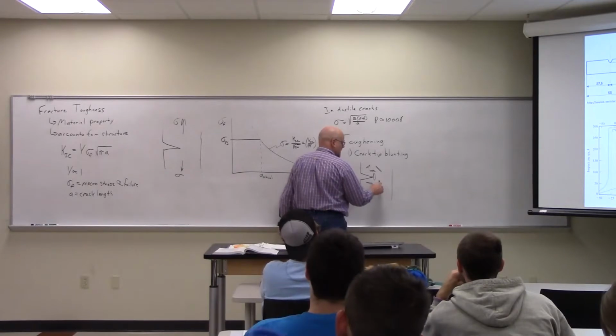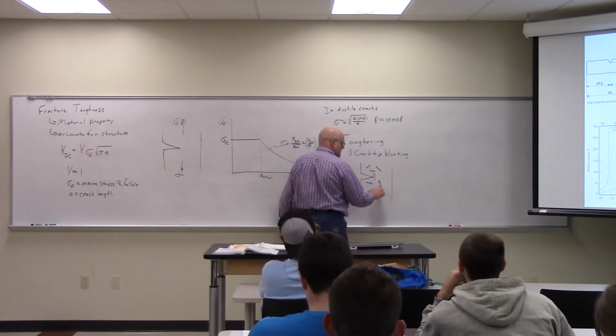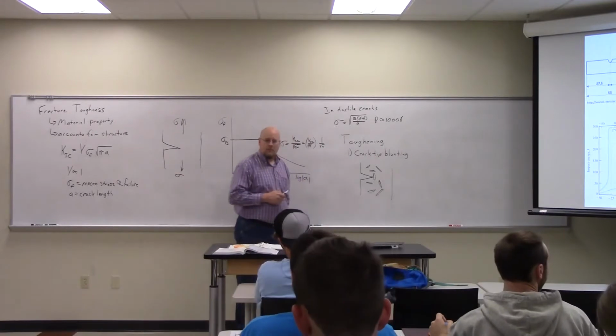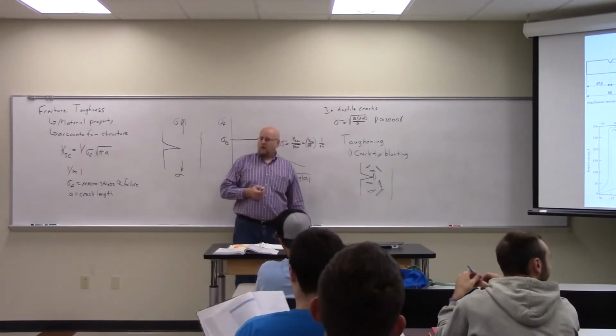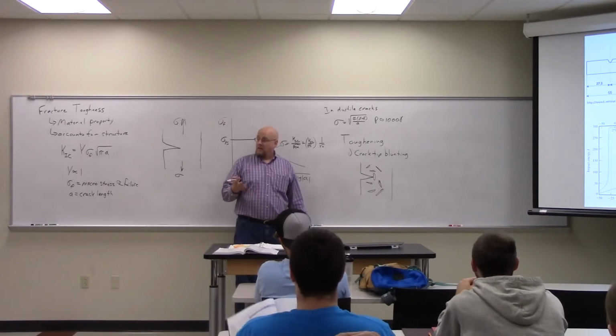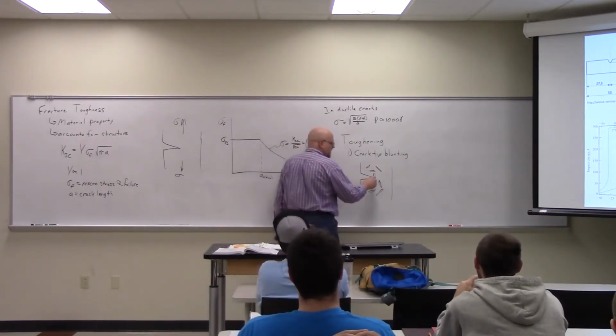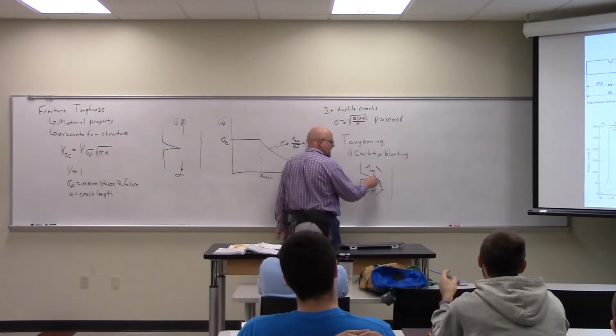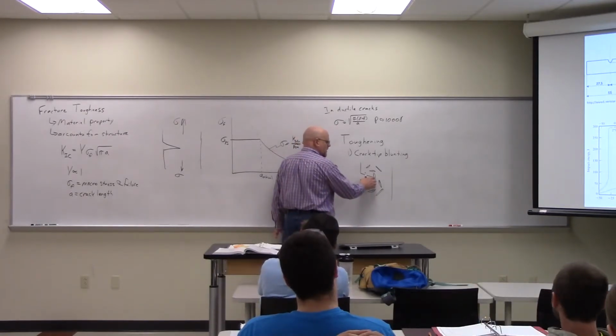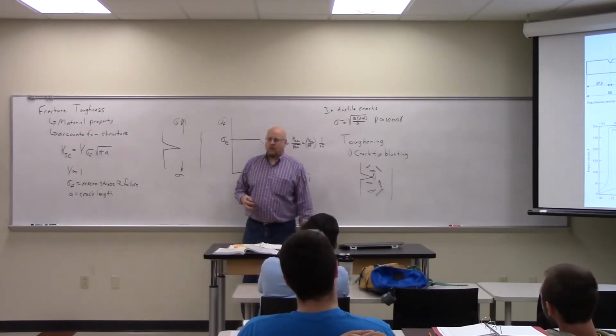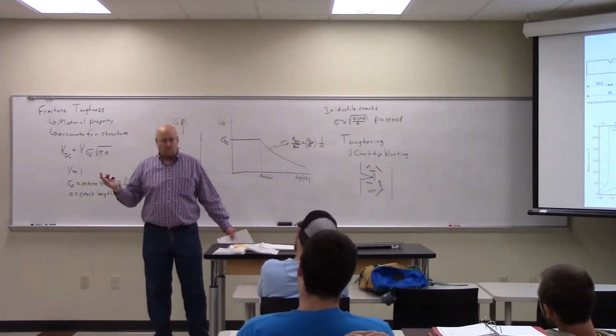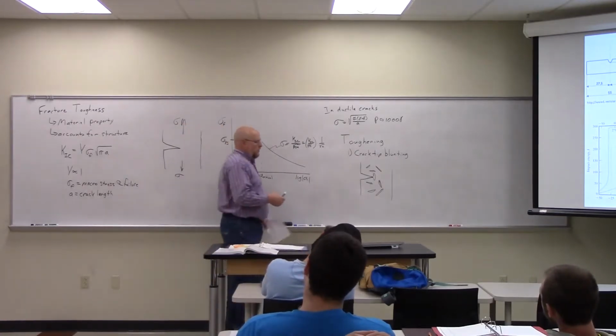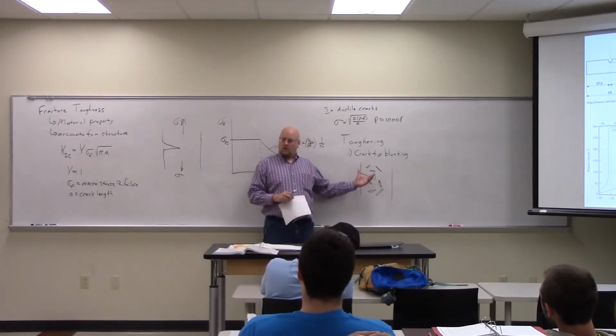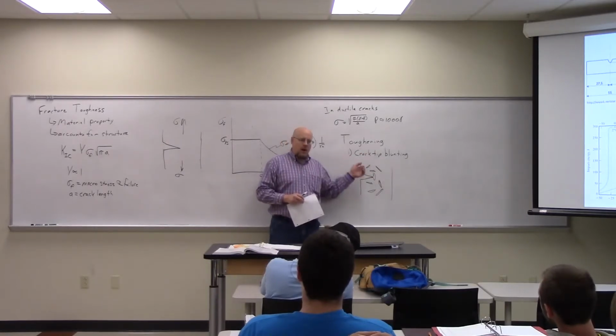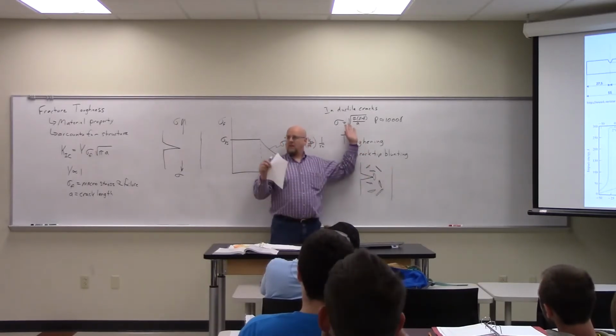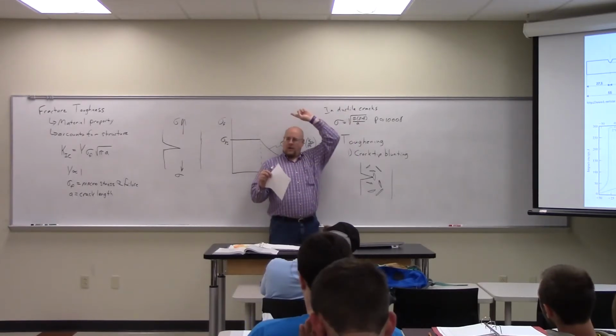Like this. And then obviously the size here is exaggerated, but you get the general idea, right? So you have all these micro cracks in the material. You'd think that'd be a bad thing. But the nice thing about the micro cracks is when a big crack starts to propagate, it eventually encounters one of these micro cracks, and when it opens it up, I've just increased the crack tip radius of curvature hugely. I've blunted the crack. So these materials are typically fairly tough, considering what they are, because the cracks can't propagate as sharp cracks all the way across. They hit something and suddenly they're no longer a sharp crack. Stress concentration goes way down.